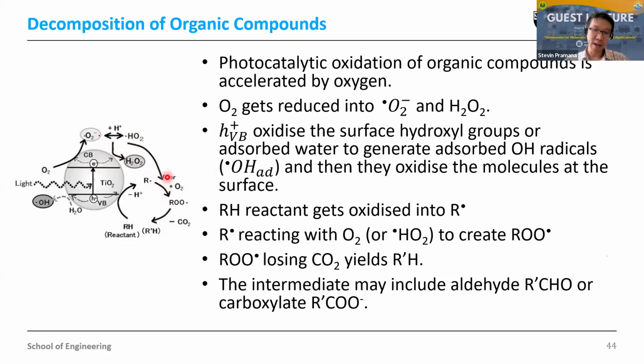For example, R dot reacting with this O2 minus or HO2 minus will create ROO minus in the presence of oxygen. And after you get the ROO minus, the normal photocatalysis or decomposition process takes place. The R here will lose one carbon, typically producing carbon dioxide, CO2, and as a result it will produce R prime H. So for the alkyl group, you are losing one carbon. The intermediates from this typical reaction are not only a simple product like R prime H. They can involve, for example, aldehyde, R prime CHO, but also the carboxylate form, R prime COO minus.